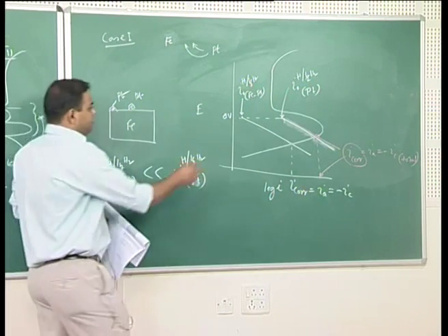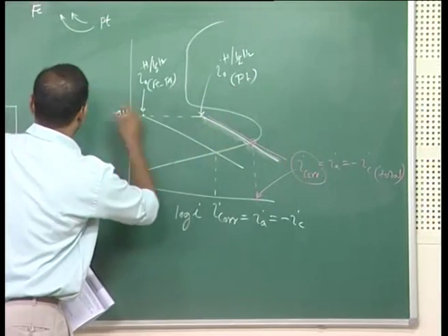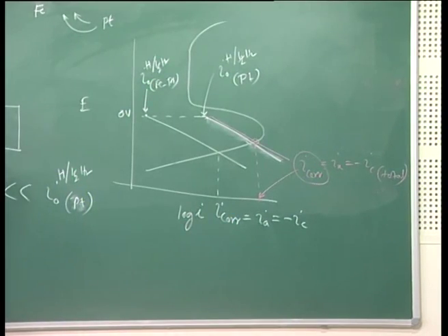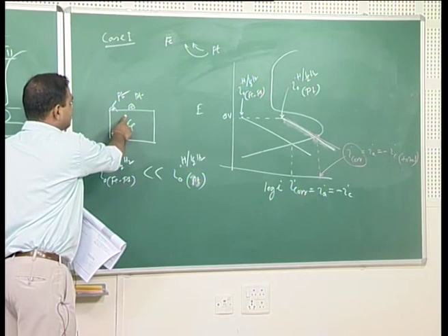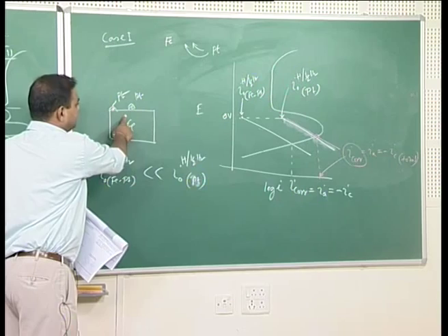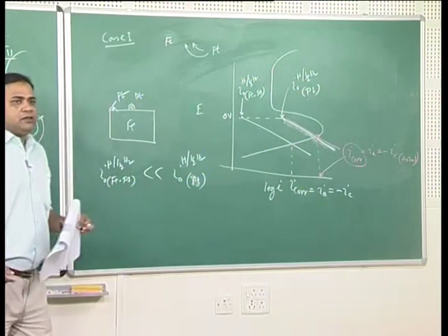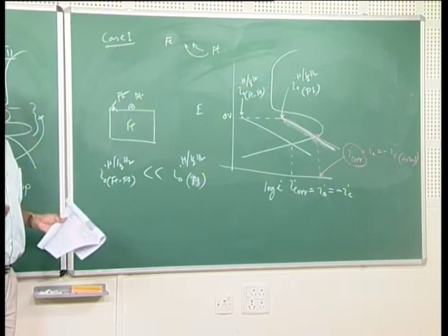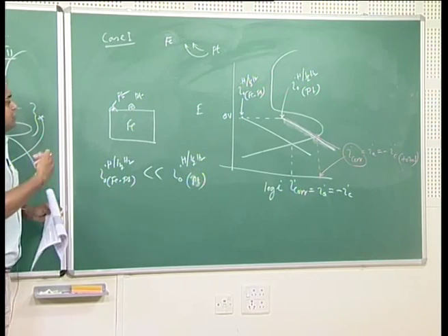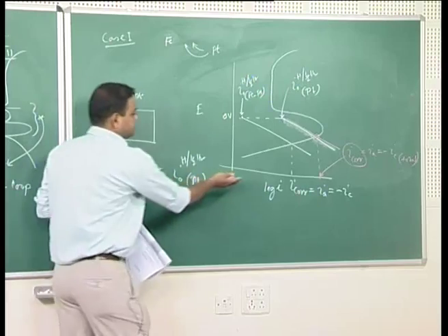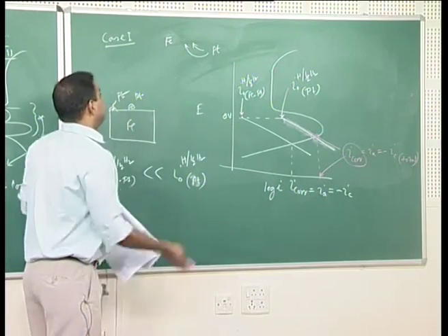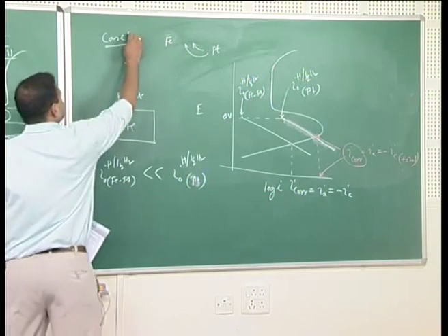So, here after this situation, dealloying and platinum enriched zones on the iron surface, my corrosion rate of iron or that alloy increases very much. It increases to a great extent, because this is in log scale. So, here it gives a negative effect. This is case 2.